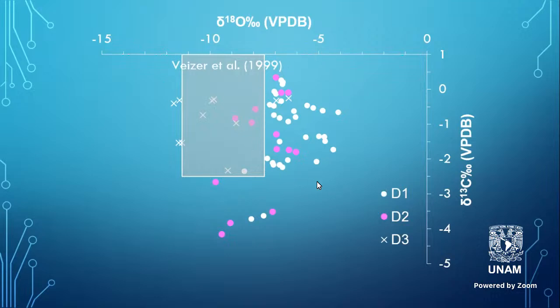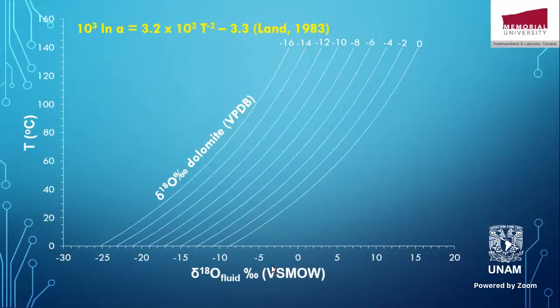This is not strange because dolomitization is always associated with enrichment in the delta oxygen-18. This is a mineralogical factor that controls the delta oxygen-18 during dolomitization. Well, the equation by Land in 1983 relates the temperature to the delta O18 of the fluid and also the delta O18 of the dolomite. If you know the delta O18 of the dolomite and the temperature of dolomitization, you can calculate the delta O18 of the parent dolomitizing fluid.